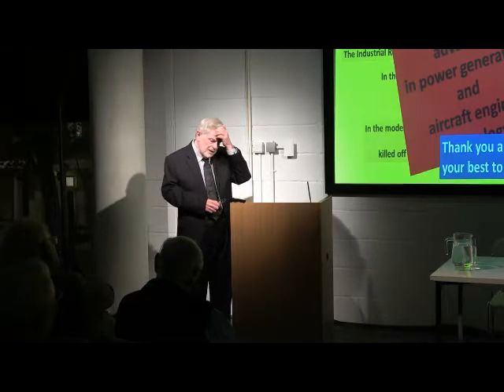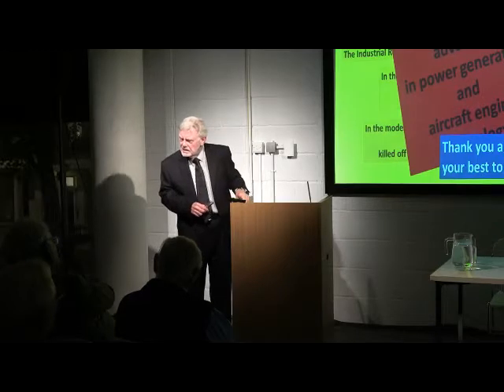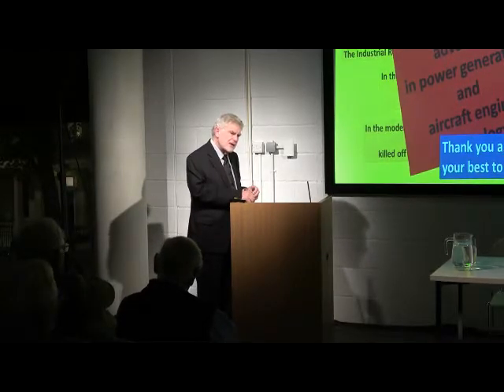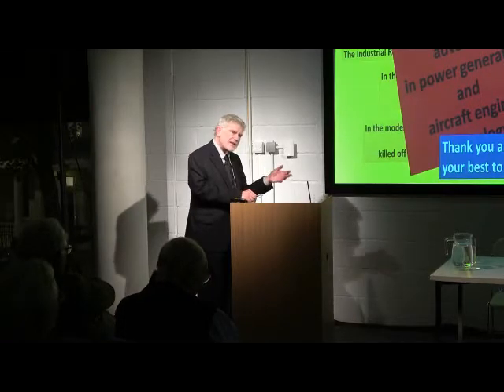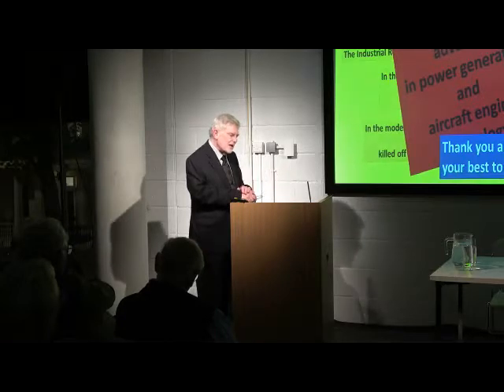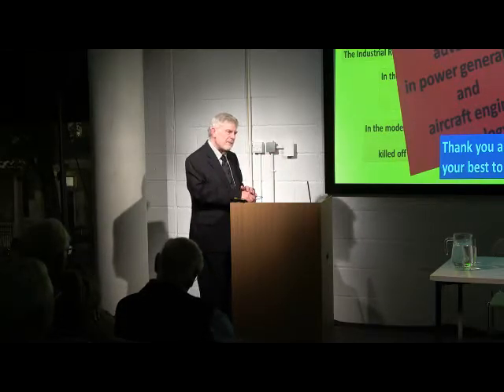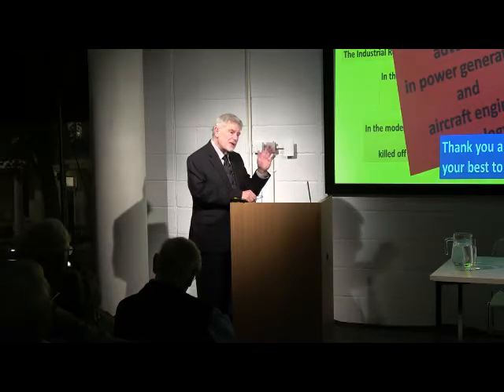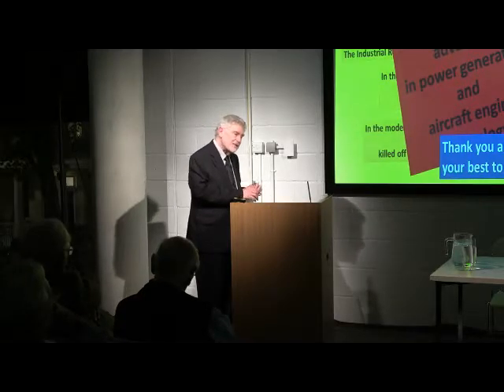Well, I think Jonathan said, are you going to say anything about stainless steel? Well, stainless steels were invented around about 1906, something like that. What would become very apparent very quickly is that these materials not only had good resistance to rusting, but when they were heated up in the furnace, the scales that formed were really quite thin. And so you start to put two and two together that if you added enough chromium to the alloy, you'd get better oxidation resistance. And you have to add enough. You need about 12% chromium to give you good oxidation resistance. If I can have a snipe at Rolls-Royce again, this super alloy they're using in the Trent has got 2% chromium.